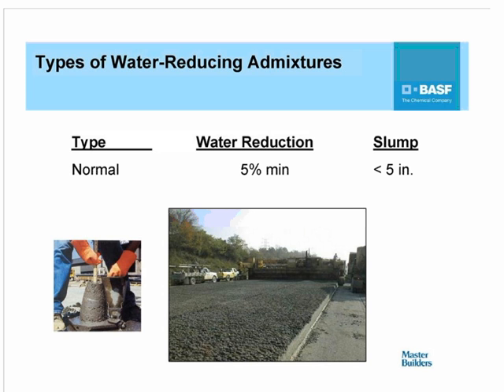Now, when we start off with the Type A or the normal water-reducing admixtures, these, by specification, have to provide a minimum of 5% water reduction when used in concrete. And they're used primarily in concrete that would typically have slumps of no more than about 5 inches. They can also be used synergistically with other types of admixtures within the concrete portfolio.